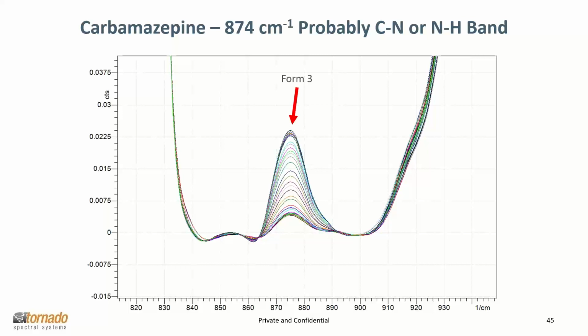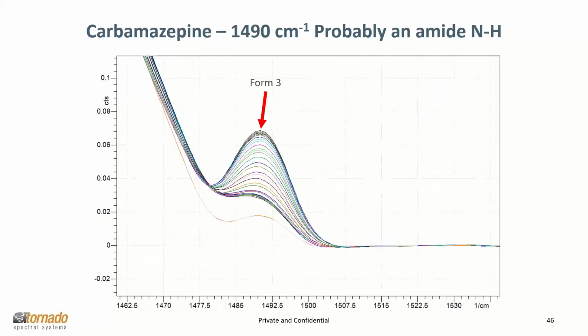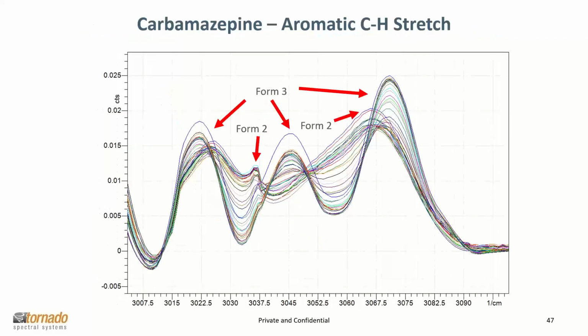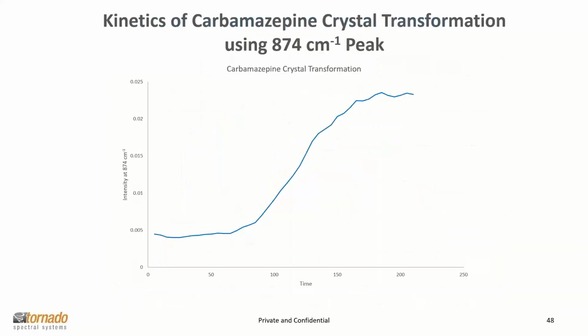There's also some other peaks that are of interest here. There's a peak in the region around 874 wave numbers that's strictly related to form 3. So that becomes a very nice distinct peak to follow. There's another one in the 1490 area, probably an amide band, where we can also see it's distinctly related to form 3 as well. And then in the aromatic CH stretching region, we see something similar to what we saw in the lattice bands, where you're looking at spectral pattern changes that allow you to follow the process very distinctly as well.